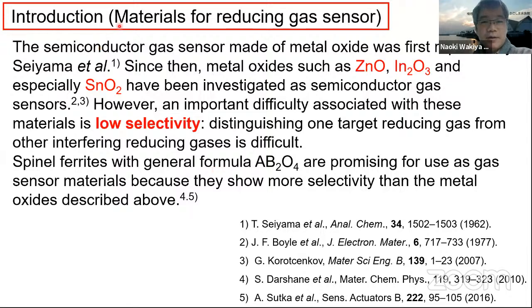And there are many materials for reducing gas sensors. For example, the first gas sensors were reported using zinc oxide, In2O3, and SnO2, tin dioxide. However, an important difficulty associated with these materials is low selectivity. Selectivity means distinguishing one target reducing gas from other interfering reducing gases, which is difficult. So spinel ferrites with general formula AB2O4 are promising as gas sensor materials because they show more selectivity than single metal oxides like SnO2 or zinc oxide, because we can choose the A and B elements.